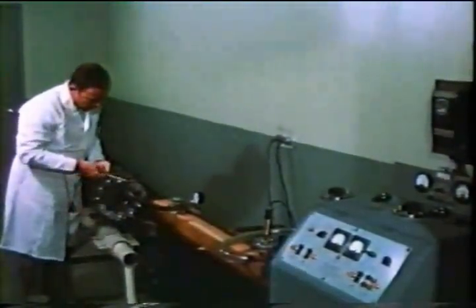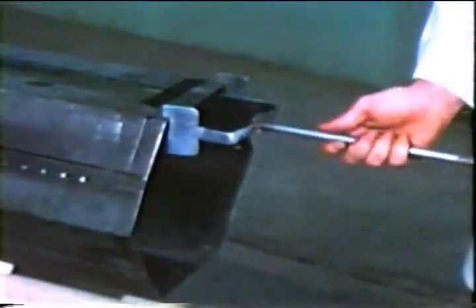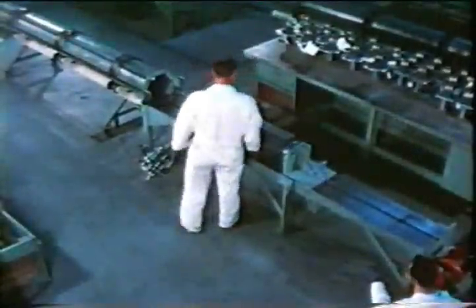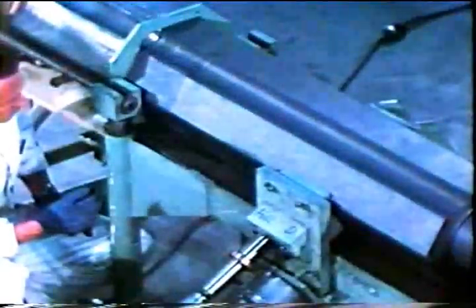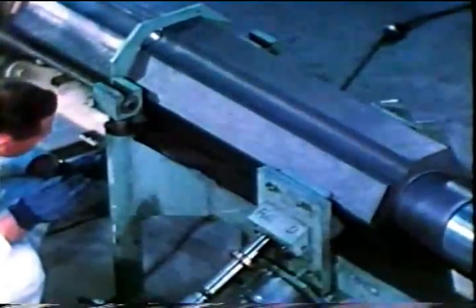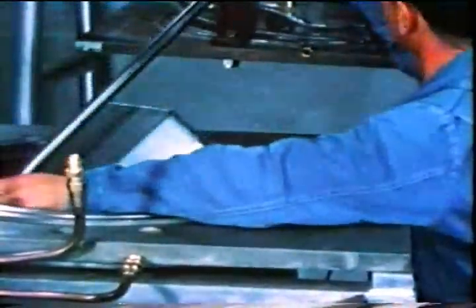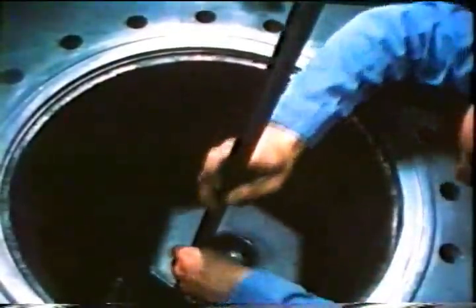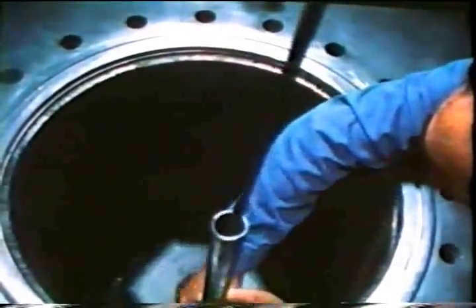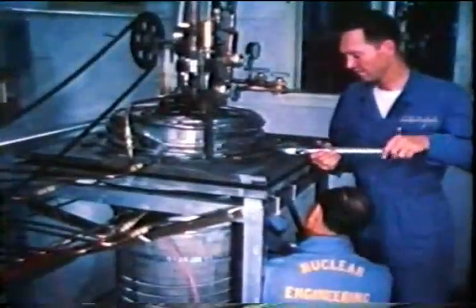All moderator cans were thoroughly leak tested, since a leak would allow absorption of sodium by the graphite and cause excessive neutron losses. The welds were also X-rayed to check for porosity and contamination. Three graphite blocks comprise the moderator element for each can. Short sections of moderator cans were used to determine the durability of welded head assemblies. Through these tests, improvements were made, and final heads survived tests equivalent to 8 years of operation in the SRE.